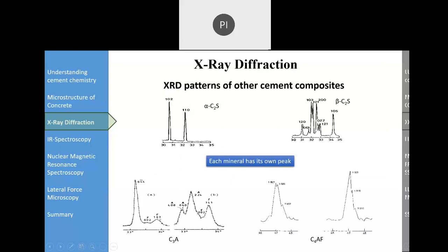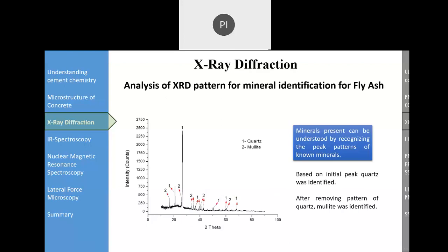So different ranges. This is XRD for fly ash, which we did in the laboratory. And we could easily identify that it has mainly quartz and mullite in itself. So the different peaks of quartz and mullite, which we got in XRD.